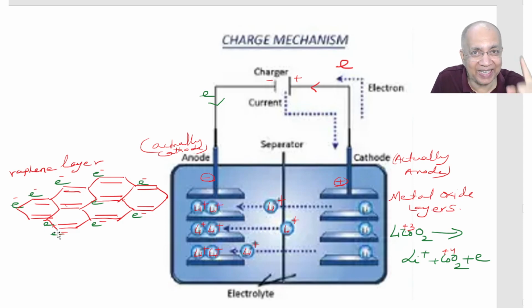But the magic is that electron will not reduce lithium ion to lithium metal, because this gap is quite high, about 3 angstrom. So electrons cannot jump of their own. They will remain confined in the carbon skeleton and it will be electron rich, and hence increase the oxidation potential of this electrode, which is now going to be anode. But now, as long as charging is going on, it is acting as cathode. It is accepting electron, becoming enriched in electron, and lithium ion being housed, intercalated in between the graphene layers. The beauty is that lithium ion does not undergo a reduction.